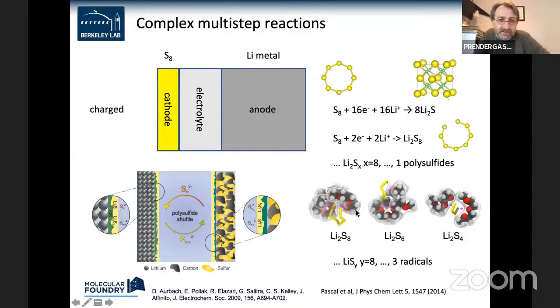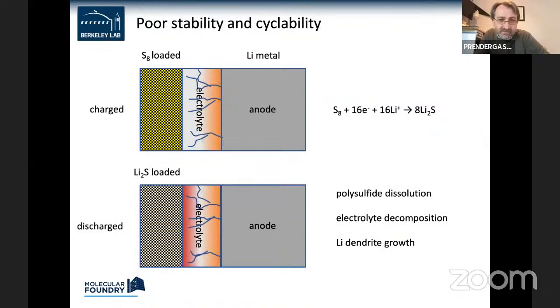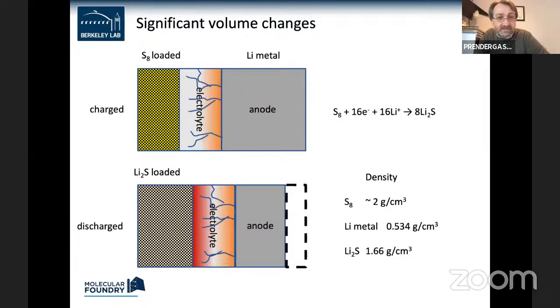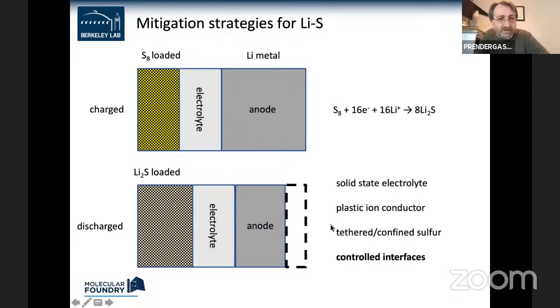And the sad news is that these polysulfides dissolve in the electrolyte. And so you begin to lose active material over time as the cell cycles. And that leads to problems with decomposition, and the cells fail over time. So that's why there's not a huge amount of commercial lithium sulfur out there. One other thing is that there's big density differences between the different species. So as you move lithium back and forth, typically the anode is lithium metal, there would be gaps in your cell if you work out the densities. And so really what you need to have is some kind of spring-loaded cell to keep all of these objects in electrical contact so that they can still function. And that's done, actually. The test cells that you see often have a spring inside them to keep the materials together, or they're screwed together with some finite pressure to keep everything in electrical contact.